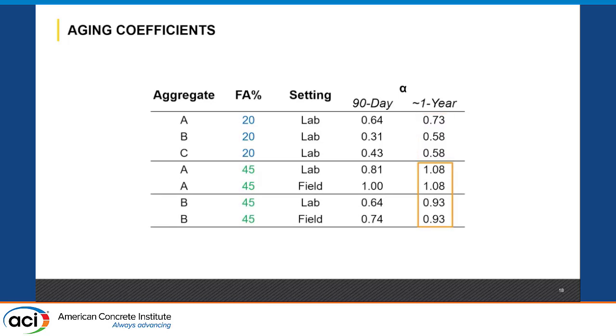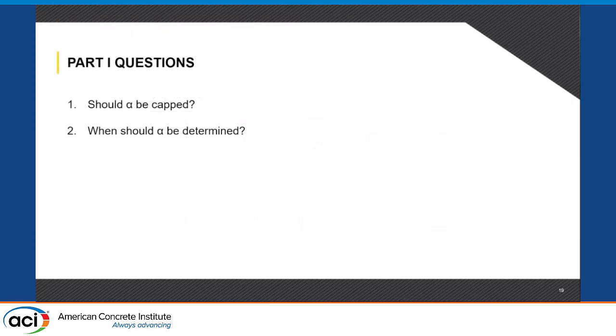So this shows that at 1 year, this fly ash was super consistent. I mean, this is mock-ups in the field and in the lab halfway across the country. This was just remarkable to be able to match these results. And I did check that it was not the same set of data. So again, this is saying fly ash is great. And if you measure it for a year, I think you have really consistent, reliable data.